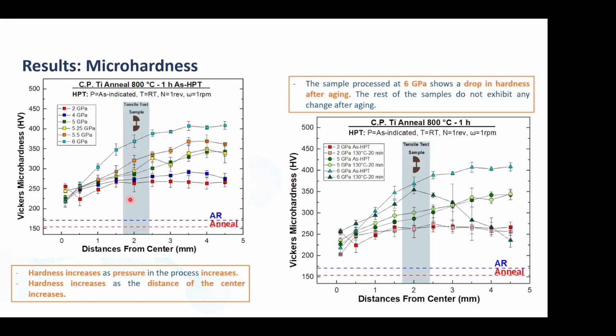Just as a schematic here, this is the area of the disc where we usually take our tensile test. So we can compare the hardness that we get here with the actual testing of the tensile strength. And then if we age it, something interesting happens. As I said before, the microstructure evolves firstly at the periphery. Usually this is the area with more defects, dislocations, and when we heat treat it, this is the area that recrystallizes, statically recrystallizes first.